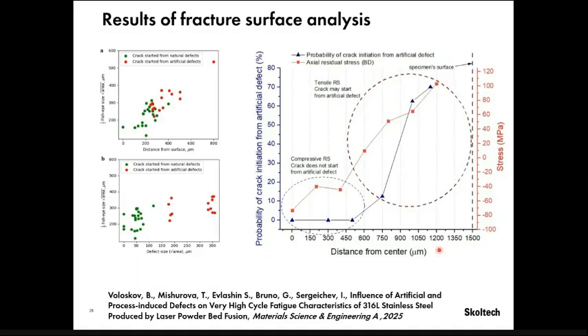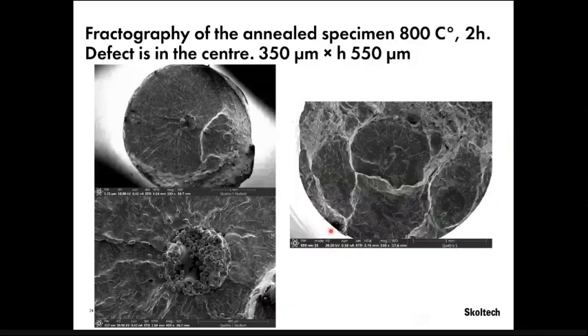versus distance from center. So we can see that where we have the compressive residual stresses, we don't have any crack initiation from the artificial defect. Then we shift it closer to the surface, to the tension zone, and we can achieve crack initiation from the artificial defect. And it was also supported by our new results, which are for annealing. We annealed our specimens, so we stress relieved them, and we started to achieve this crack initiation from the central defects, as you can see here.